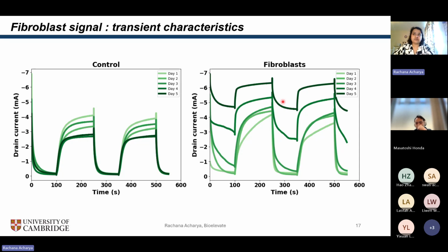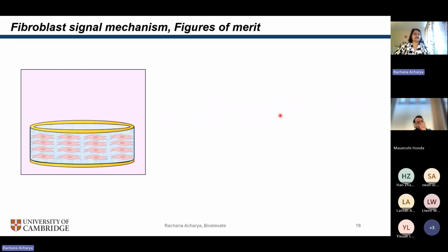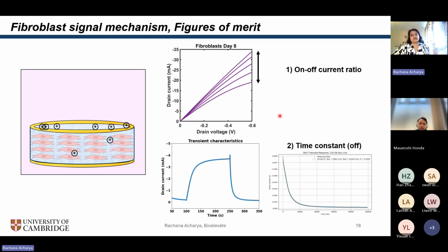So that is again what we would call a characteristic signal for the growth of my cells within my device. Let's have a look at why this is happening and hypothesize what must be the mechanism of this electronic signal. The hypothesis is that as the cells are growing, they're covering the layer of the polymer inside the scaffold, also secreting a lot of proteins which act as a barrier. Then when I try to polarize my electrolyte, it's blocking the flow of my positive ions into the polymer, which, if you remember, is what switches the transistor off. So the growth of the cells is actually blocking access of the cations to the polymer, which is preventing the transistor from switching off.